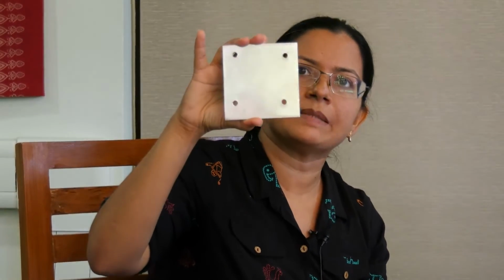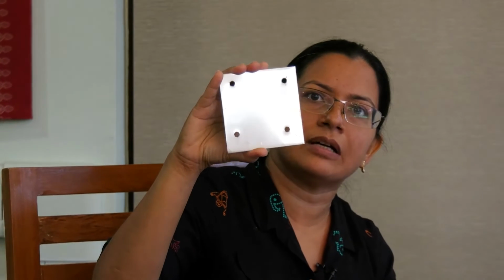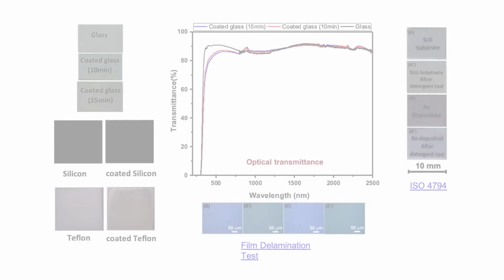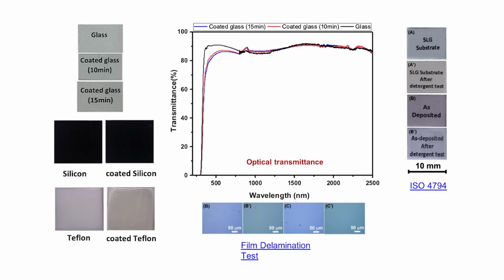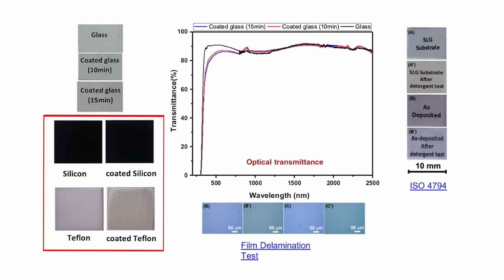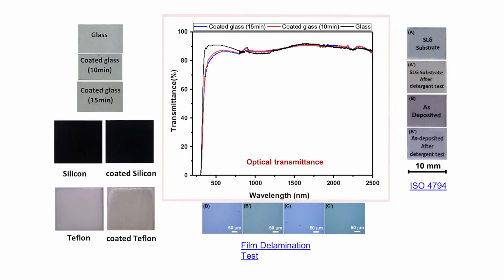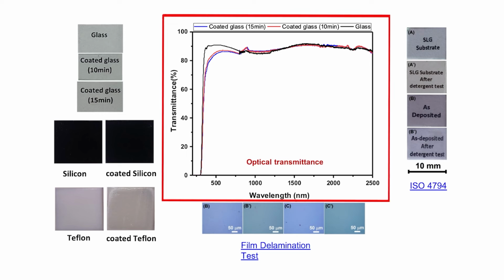This coating has been developed on the glass substrate, and this is also an aluminum substrate on top of which the coating has been developed, and you can see that it has not changed. Similarly, you can see on silicon and on Teflon, the nature of the base material remains unchanged. This is how the optical transmittance looks, and you can see that the material has very good transmittance.